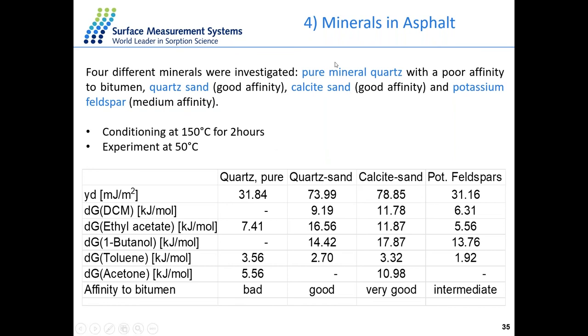And here we have four different materials: the pure quartz sample, the quartz sand sample, the calcite sand sample, and the potassium feldspar sample. Here we find the two minerals in the middle have very good affinity with the binder, and the pure quartz sample has the worst affinity with the binder. Then we performed the same IGC experiment for all four samples at 50 degrees, with preconditioning at 150 degrees to remove the moisture for 2 hours.